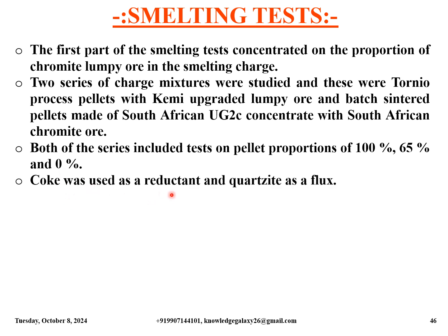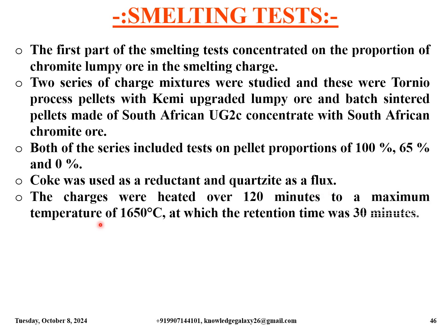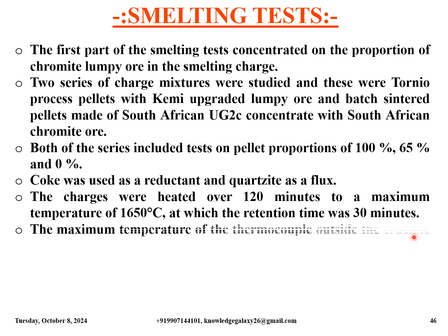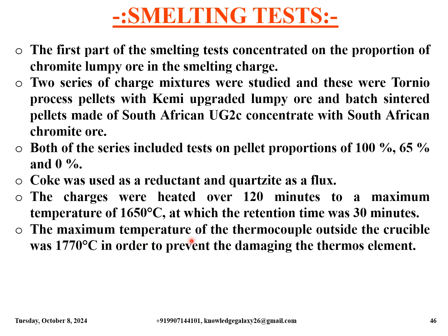Coke was used as a reductant and quartzite as a flux. The charges were heated over 120 minutes to a maximum temperature of 1650 degrees Celsius, at which the retention time was 30 minutes. The maximum temperature of the thermocouple outside the crucible was 1770 degrees Celsius, in order to prevent damaging the thermo element.